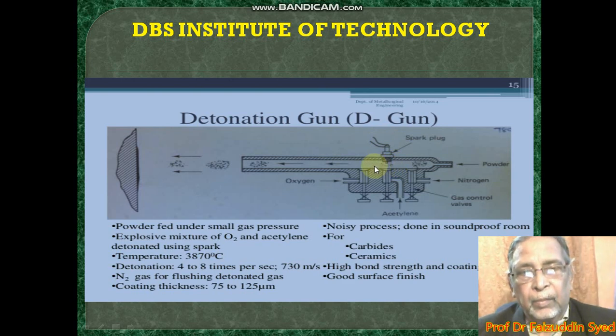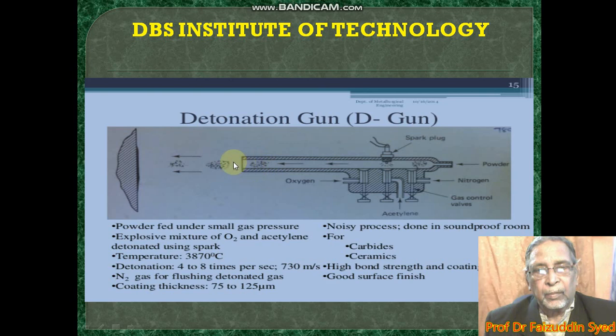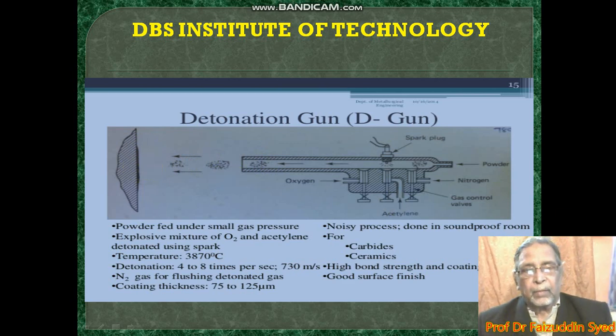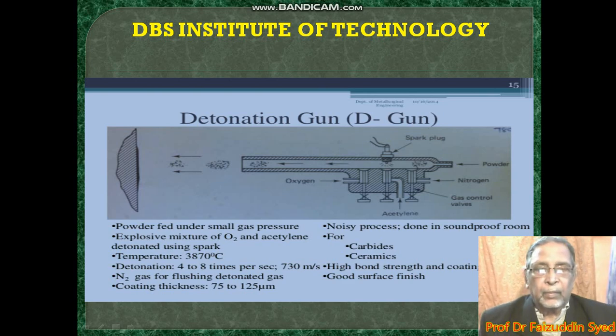The temperature is 3870 degrees centigrade. The detonation is 4 to 8 times per second, at 730 meters per second. Nitrogen gas is used for flushing the detonated gas. So you are using nitrogen gas for flushing purposes. The maximum coating thickness we can do is 75 to 125 microns.